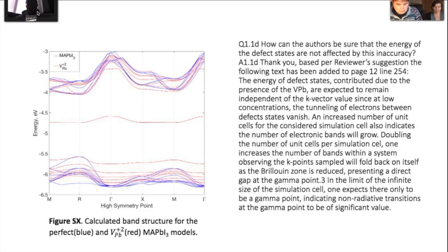But because of this defect, within the valence band there's now this raised-up energy of these states and an increased spacing, making it closer in energy to the top of the valence band at the R point. I'll talk about that a little bit in these next couple slides.